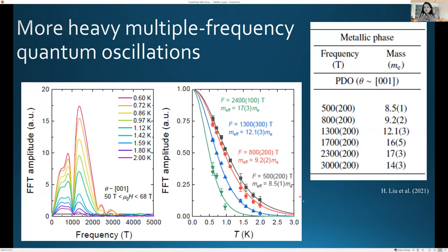And so what this shows is that even when the material becomes metallized, it hasn't lost its hybridization, which is very unlike the SmB6 case where we were getting these large Fermi surfaces, which were light. In this case, even in the metallic case, it's interesting because what it looks like is the insulating state Fermi surface is in some sense mirroring the hybridized heavy mass metallic Fermi surface that we access at high magnetic fields.